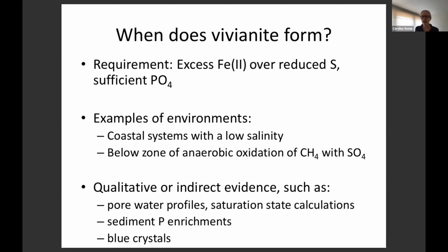Now, if we look at what evidence we have for vivianite in marine sediments, and actually in lake sediments too, it's quite difficult to prove that vivianite is there. People often use pore water profiles and saturation state calculations from that. They use sediment phosphorus enrichments, and they often use observations of blue crystals, because vivianite turns blue when you expose it to oxygen. And those blue crystals are then used as indications of vivianite.